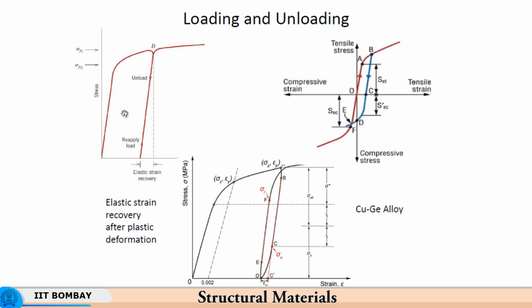but if your material crosses the yield point, then let us say you take a wire and bend it to a very sharp angle of bend, then there is a plastic deformation in the outer fiber, and when you reverse the stress, the outer fiber will yield at a much lower stress as compared to the previous cycle. So, naturally it will get softer and softer progressively, and then it will finally break. Why will it break? Because the yield strength will practically come to 0, and then when you just apply some amount of force, it will break into 2 pieces. So, this is the technique we use for breaking a wire.